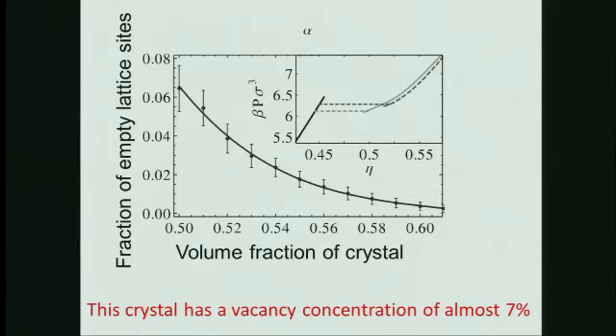So this is an amazing thing, that although it's perfectly ordered, actually this thing is full of vacancies. And at the melting position, this system has almost 7% of all lattice sites not occupied. To my knowledge at least, in a pure system of simple atomic or molecular systems, there's no equivalent.